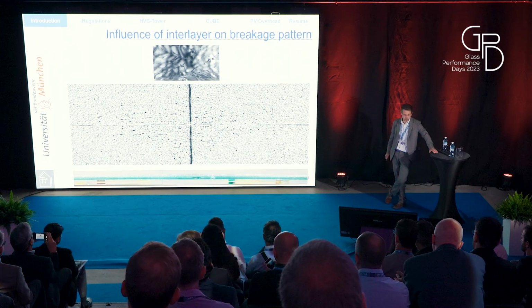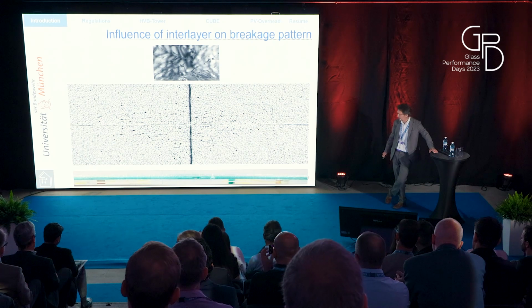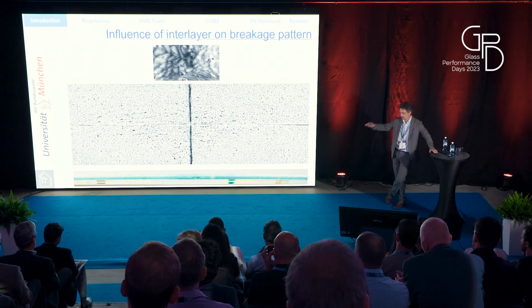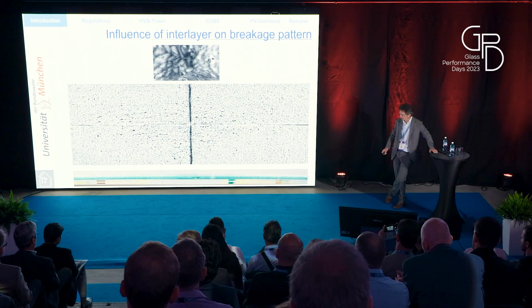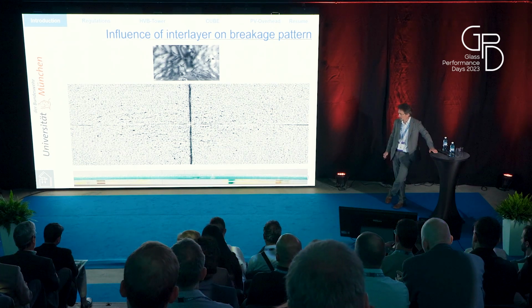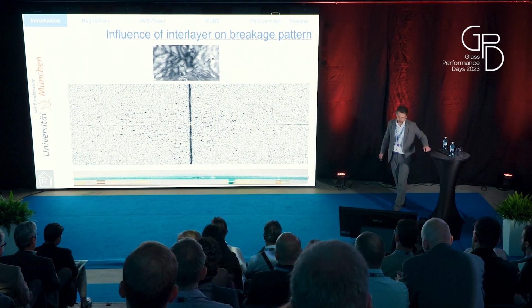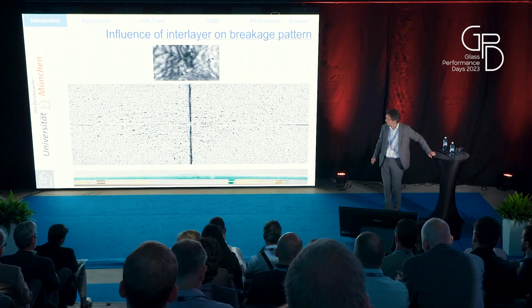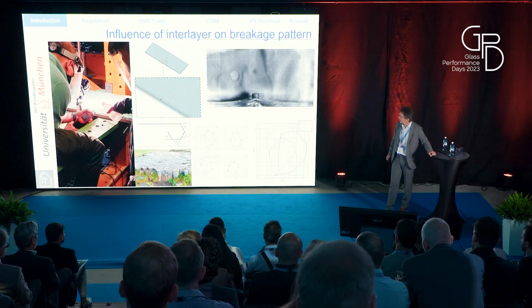This is a laminate of two glasses, and you see in the broken situation, of course, there is this bending of the material of the broken glass because of the volume expansion. And as I said, the question is: is there any effect of the interlayer? And here again, we did some research.